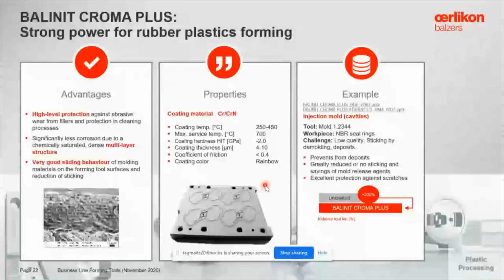Here is an example. You can see the tool steel is hot die steel, and this is an NBR seal ring. Here we prevented the deposit formation, greatly reduced the sticking, and gave excellent protection against scratches. So almost a life improvement of 3 times.